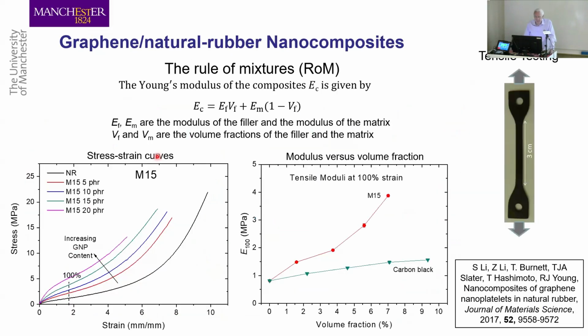So let's look at some simple measurements we've done. We've looked at graphene and natural rubber. We've taken natural rubber, added some graphene to it, and so we have a tensile test here, black specimen, stretches in the vertical direction. And what we've done here, we've got a series of stress strain curves of natural rubber, the black one here, and then natural rubber with different loadings of graphene nanoplatelets in the material. And you can see that as you add graphene nanoplatelets, the material becomes stiffer, which is what you might expect. You get that with carbon black, but it's better than carbon black. It does give quite a lot of stiffening, even at low loading.